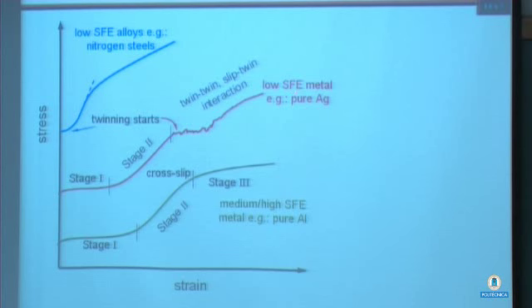Now, if you look at a low stacking fault energy metal like silver, lead, it looks like this. Stage 1, again, is present. Stage 2, where the slope is higher. And then, at some critical value of stress, you initiate twinning in these materials. And then you get, of course, twin slip interactions, or twin-twin interactions. As you note here, you get the onset of twinning, and then instead of this decrease in slope, you could get a higher slope. So you could design some materials which give you enhanced properties.